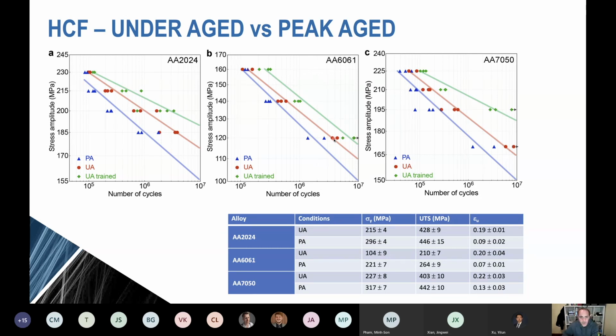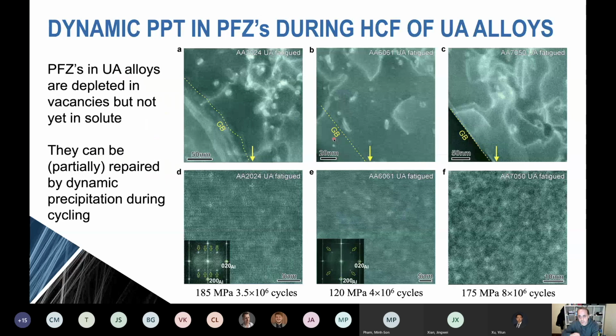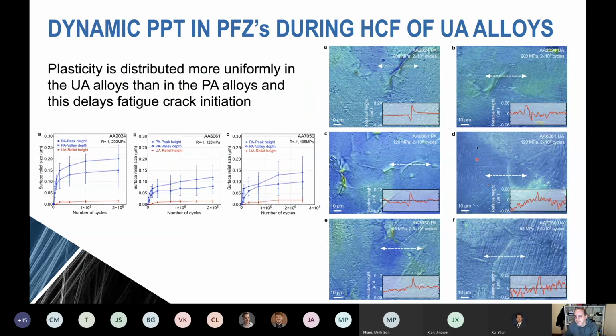And so if we look at the microstructures, in fact, we can indeed see that within the precipitate-free zones for each of these alloys after fatigue, we have dynamic precipitation. And we also see this very clearly in analysis of optical profilometry of the surface. And so what we have here is a series of optical profilometry across grain boundaries in peak age states, 2024, 6061 and 7050 after cycling.